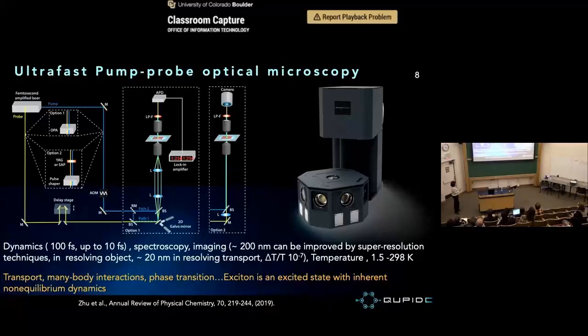One is called a pump, which is coming in to photoexcite. So that's how you create the exciton. And the probe is like an imaging pulse, coming in to look at where those excitons are. We can do this in different ways. We can scan the pump and probe relative to each other, or we can use a focused pump and a wide-field probe to look at where those excitons are.